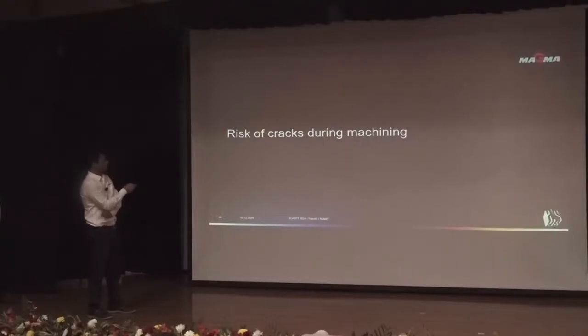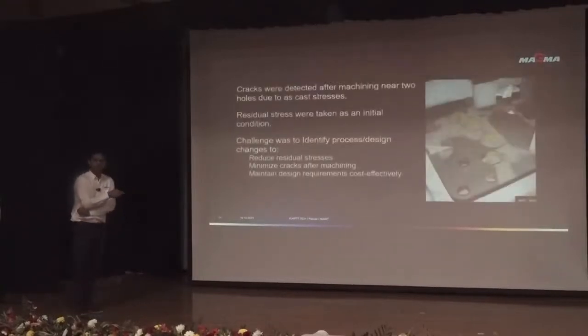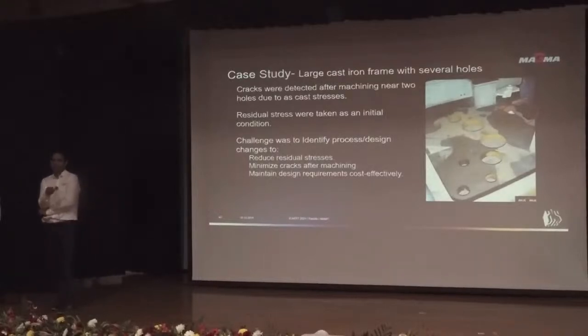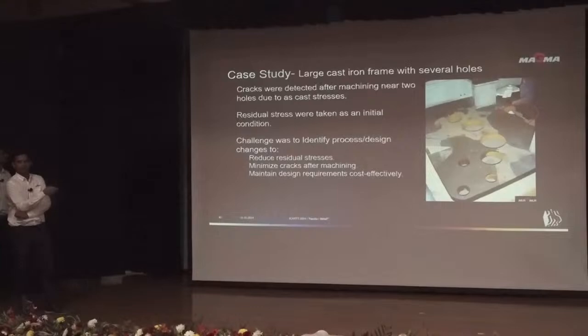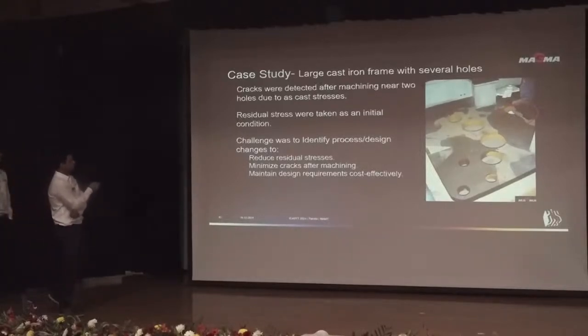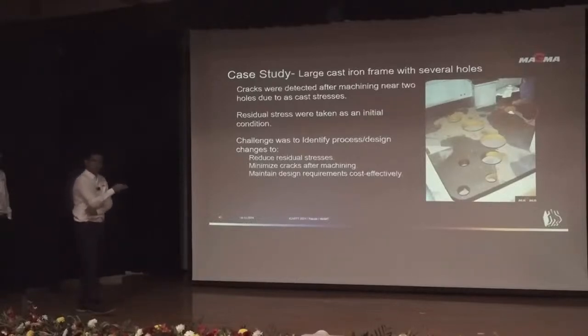Risk of cracks during machining. What happens is that the casting might be okay, but after machining we found that cracks developed in the casting. So there is another case study where there is a large cast iron frame. It has several holes. Once we cast it, it was okay, but when we started drilling and other operations, cracks appeared and the casting got rejected.